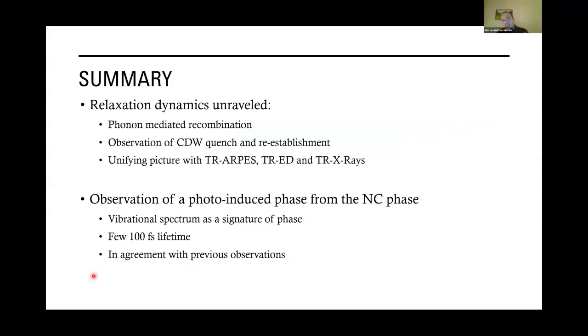So overall, I have presented a complete picture of the relaxation dynamics. We highlighted the fact that the relaxation experiences a bottleneck due to phonon-mediated recombination, due to the fact that the band that is at the Fermi level doesn't intersect with any of the valence band. This is particularly interesting because the phonons that are required in order to do the recombination are phonons linking with large momentum from the gamma to the M point. When we cool down the temperature, these phonons are going to be less populated, which could explain the long lifetime of the photo-induced hidden state of tantalum disulfide. We also observe the charge density wave quench and reestablishment inside the transient reflectivity.